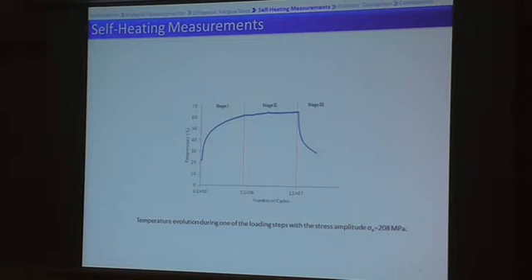Here you can see the temperature evolution for one of the loading steps as an example, with the stress amplitude of 208 megapascal. As you can see, there are three main stages. In stage 1, the temperature increases and then it reaches a steady state at stage 2. This steady state corresponds to a balance between the mechanical energy dissipated into heat and the heat losses through conduction and convection. And afterwards, in stage 3, we can see the cooling of the specimen after stopping the load, and we will use the slope of the cooling just after stopping the load in order to measure the dissipated energy, as I will explain later.